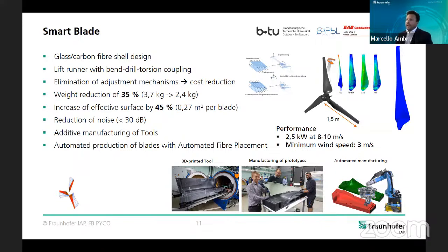So what is the performance? We have 2.5 kilowatts at 8 to 10 meters per second, and a minimum wind speed of 3 meters per second. So as you can see, we already match these low regions here for the installation of this rotor blade. And the specific feature is that we integrated a bend-twist coupling to avoid all these adjusting mechanisms or brake systems which cost additionally.